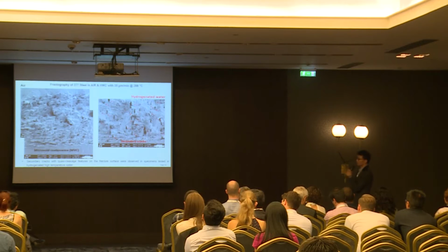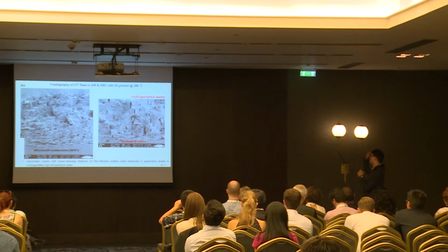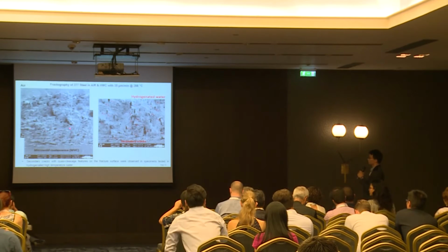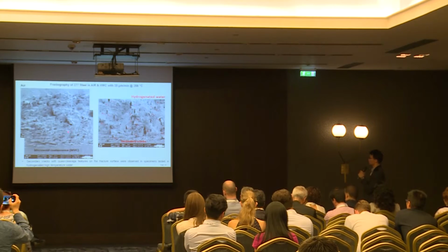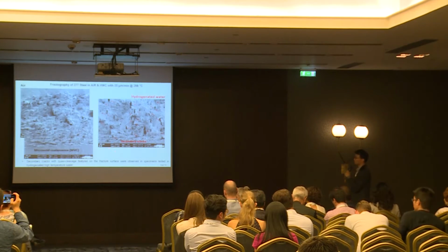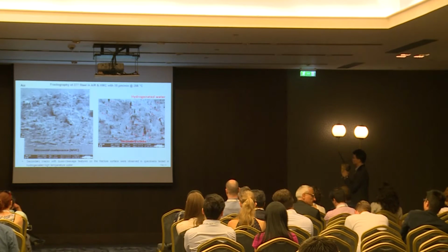After the test, we break the specimen and we see a very distinct change in the fracture surface. For the test conducted in air, the fracture surface was mainly dark with mainly microvoid coalescence. However, in the hydrogenated water chemistry, a lot of secondary cracks with quasi-cleavage were observed.